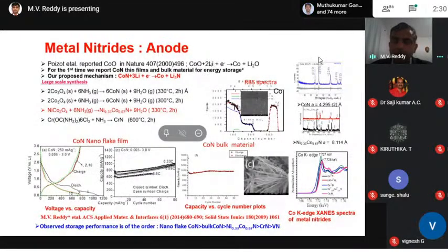I think I have another 5 minutes, so I'm going to go through this quickly. Next, nitrides: we try to prepare samples either as thin films or as bulk material, such as cobalt nitride. Again, thin film seems to be better, because we are able to get nano size, whereas for bulk material the capacity will be lower. The main issue is that voltage hysteresis is a big problem. Although we claim that 3 lithium can be reacted using nitrides, giving higher capacity, compared to oxides it is lower. The main issue is how to reduce the overpotential, which is a big issue for practical applications.